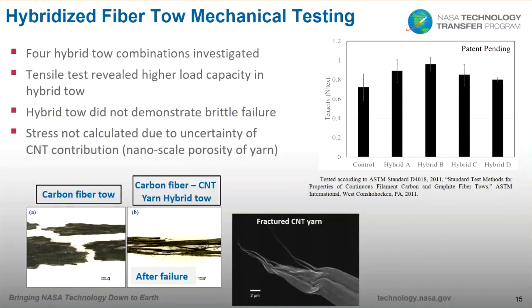Through the tow tensile test that we conducted, we noticed an increase in the load capacity and also in the shape of the load displacement curves, all indicating that more energy absorption was observed in the hybrid tows. Unlike the carbon fiber control, the hybrids did not demonstrate brittle failure.